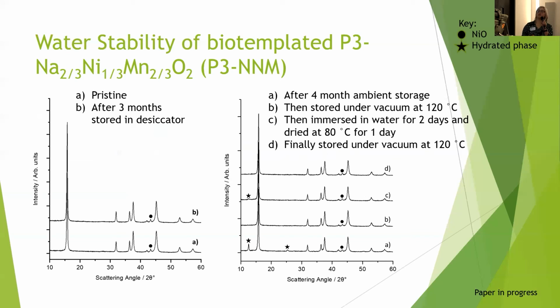So here on the left-hand side, I have XRD patterns of the pristine material versus when I just stored it in a desiccator for a few months and it showed no change. And then I went rummaging through my cupboards and found an old sample, and it was 4 months old. And I did find some additional hydrated peaks. But then I found this is really reversible, and after drying in a vacuum oven, they disappeared. And then I decided, why not just throw it in some water, see what happens. And in a regular drying oven, afterwards I did find a really small amount of hydrated phase formed there. But then again, after drying in a vacuum oven, that went away. So it's a really good candidate for water-based binders.